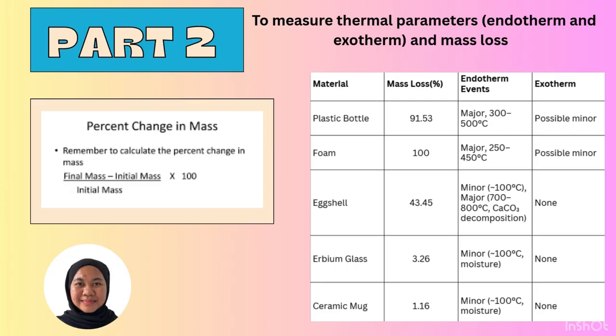For calculation part 2, to measure thermal parameters, endotherm and exotherm, and mass loss, we use the mass loss percentage formula, which is final mass minus initial mass over initial mass times 100%. Based on my data, for the plastic bottle the mass loss is 91.53%, the foam is 100%, the eggshell is 43.45%, erbium glass is 3.26%, and the ceramic mug is 1.16%.